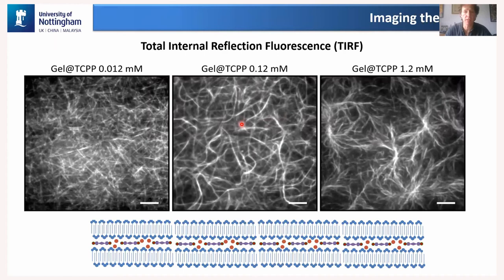And as you increase the concentration of TCPP in the water when you add it even further, you get these kind of branch structures coming off. So you can influence the morphology as a function of the concentration of TCPP that you use.